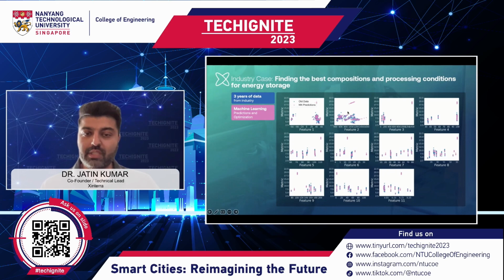Now, if you look very closely, you will see some elements of the first example that I showed, where you needed to do the experiments with some of the features in areas that were previously unsampled. Examples are things like feature 3, where you needed a significantly higher value, or features 6, 5, 9, where all of the sampling points were in gaps. And so when the customers did these experiments physically in their lab, what they showed was, yes, definitely that they did double their performance.